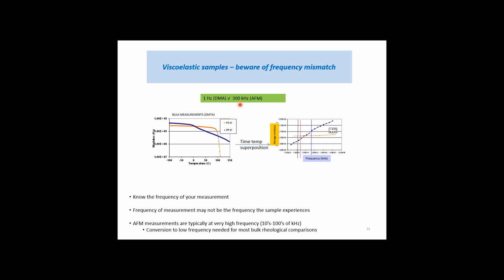And for viscoelastic materials that depend on frequency, that matters. So what, for example, in the polymer community do, we can do what's called time temperature superposition to calculate a high frequency modulus if we know the low frequency modulus at a series of temperatures. But again, the takeaway here is know and understand the frequency of your measurement, especially if you're going to be comparing it to a bulk measurement that was done at low frequency.